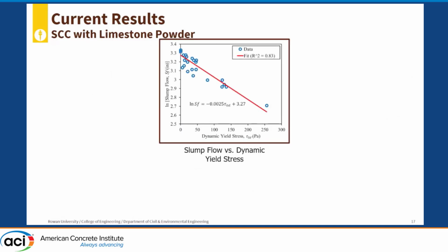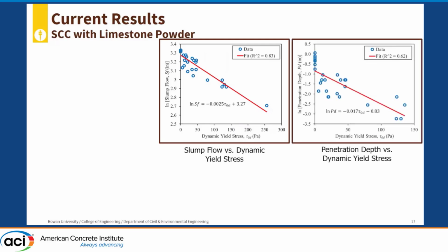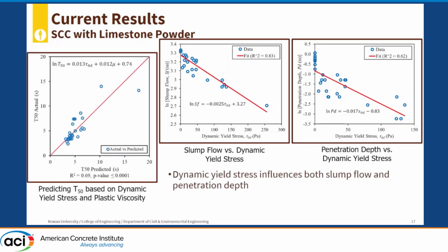With the resemblance of the rheological properties to the fresh properties, we did some regression analysis. So we have slump flow versus dynamic yield stress. As dynamic yield stress increases, workability or slump flow decreases logarithmically. We also compared dynamic yield stress with penetration depth, or segregation resistance. As dynamic yield stress increases, the penetration depth logarithmically decreases, which means you have more segregation resistance. For T50, we needed both dynamic yield stress and plastic viscosity to predict it. The coefficients reveal that if you have higher dynamic yield stress and plastic viscosity, then you have a higher T50 value.